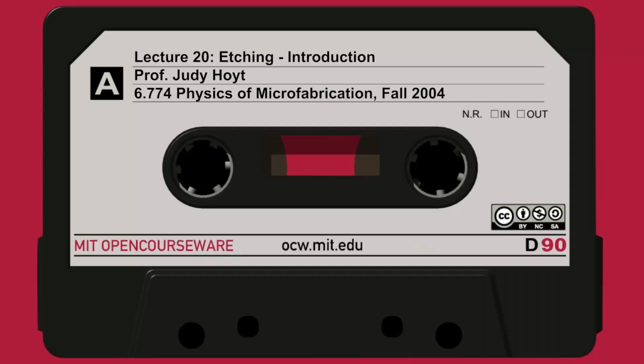Slide 19, we talk a little bit about how to control the shape or what are some of the issues. Even with ion-enhanced etching and this chemical etching, the slope of the resulting sidewall is not always perfectly vertical. There's some tricks. It needs to be adjusted empirically. The ion flux may not always be perfectly normal to the surface. The ion flux may be coming at a slight angle. That can cause bowing of the sidewalls of whatever you're trying to etch.